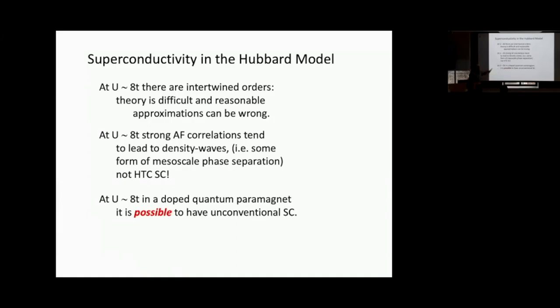I will mention one thing that I didn't put on this slide, which damps my enthusiasm a little bit, which is, at least in the case of the doped spin liquid, the sign of T prime matters. So for the undoped system, all that comes in is T prime squared. So both for T prime positive and T prime negative, we're more or less doping exactly the same phase. But for T prime positive, which is not the sign preferred for the hole doped cuprates, we find this very strong superconductivity. For T prime negative, we don't.